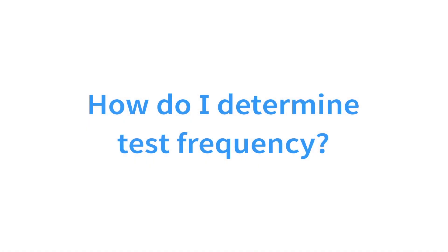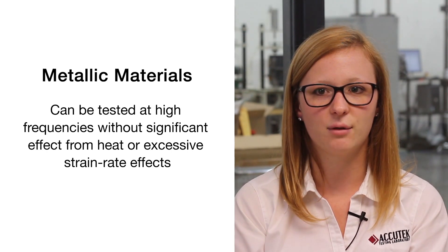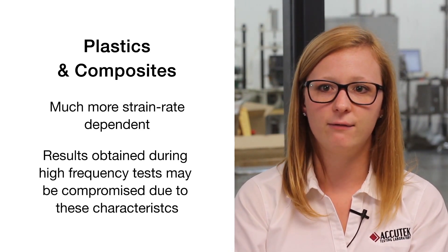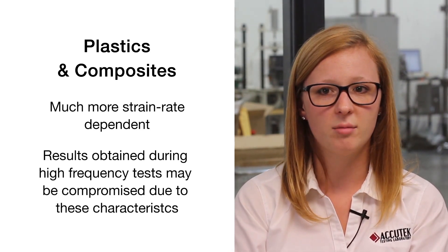Our final question today is: how do I determine test frequency? Most fatigue tests are typically performed between five and fifty hertz, or cycles per second, depending on the application and materials being tested. In general, metallic materials can be tested at high frequencies without significant effect from excessive heat. Plastics or composites, on the other hand, are much more strain rate dependent, and results obtained during high frequency testing may be compromised due to these characteristics. Additionally, products such as medical devices must be tested at even lower frequencies in accordance with applicable ASTM standards.